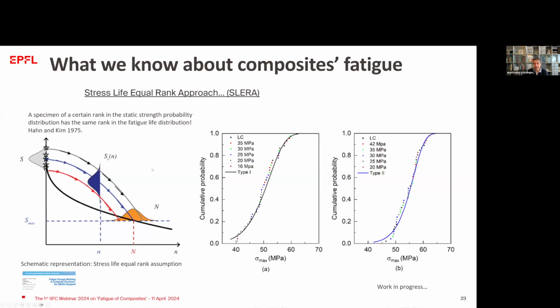So the idea behind this SLERA, the stress life equal rank approach, is that the specimen that is stronger in fatigue should be the one that is stronger in quasi-static loading as well. Although this cannot be validated, because if you test a specimen in quasi-static loading and you break it, you cannot break it also in fatigue. It is something that we've seen with statistical analysis of failures of materials at different loading types.